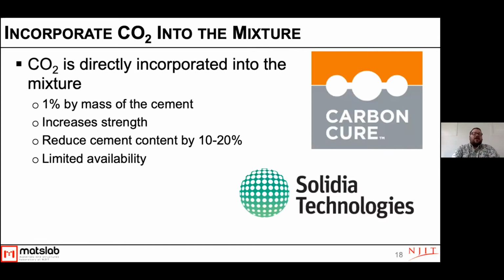The next one that we can talk about is incorporating CO2 directly into the mixture. So this is something like what CarbonCure is doing, or Solidia. Solidia is a technology company here in New Jersey. With CarbonCure, you're looking at about 1% by mass of the cement that you're mixing in CO2. So it's not actually a lot of CO2, but the key is that mixing it in increases the strength and performance of the system so you can reduce the cement content.